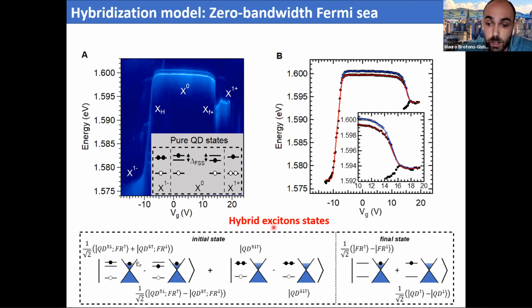So with this simple Hamiltonian, one can reproduce the energy dispersion that we observed. For this, we only need two fitting parameters, which are the tunnel coupling for the electrons and holes on this side, okay? This told us that what we have here is strong tunneling, where the electron conserves the spin between the Fermi sea and the quantum dot, and this transition conserves the spin, okay?